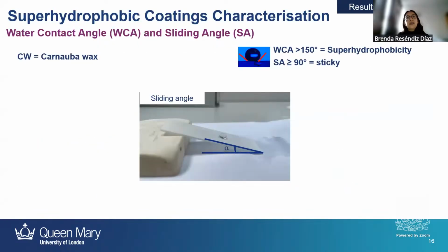For determining a superhydrophobic surface, we need to measure the water contact angle and sliding angle. To be superhydrophobic, our water contact angle should be above 150 degrees. And when we have a sliding angle above 90 degrees, that means that our surface is getting more sticky. So for getting a superhydrophobic surface, the sliding angle should mostly be lower than 20 degrees, or 10 degrees.